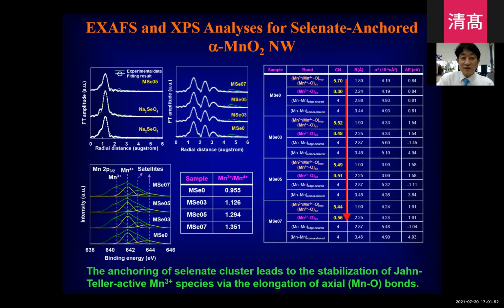We use the XAS analysis to confirm the formation of the isolated selenate nanocluster from the selenium XAS analysis, as you can see here. Also, the manganese oxide shows the typical spectral feature of the alpha MnO2 structure. Like the case of the sandwiched carbon manganese oxide nanosheet, we do the EXAFS fitting analysis by two kinds of manganese oxygen shells, corresponding to the equatorial manganese 4+ oxygen bond distance and the axial elongated manganese 3+ oxygen shells.